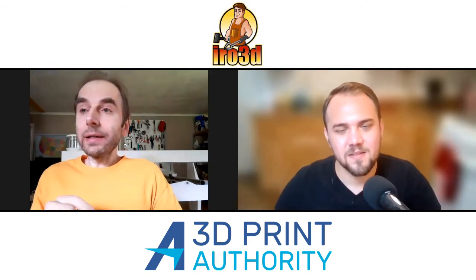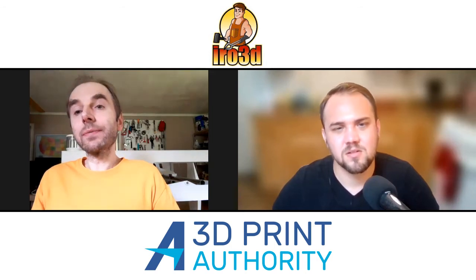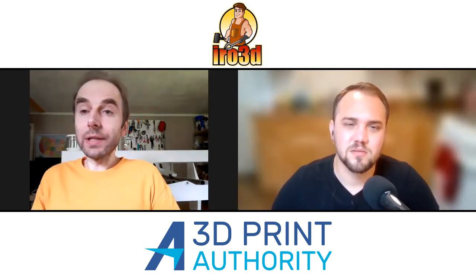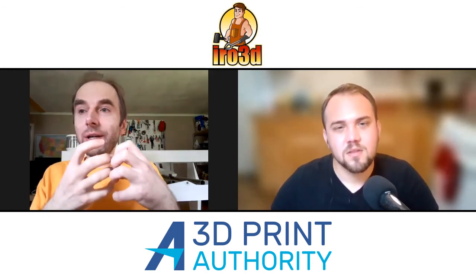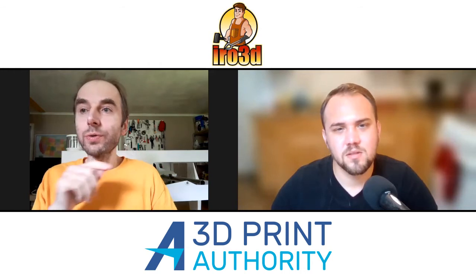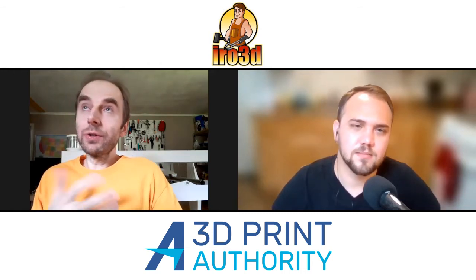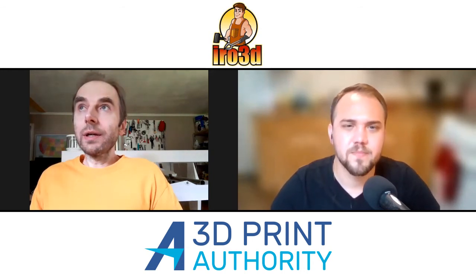Yes. And at least in theory, the parts should be 100% dense. Not with the vapor infill, but with a liquid infill. It should be 100% dense. With their process, it's not, because it solidifies, it cracks. There always would be microscopic cracks. Right. And if you just take it as is, it will not be very strong because of the cracks.